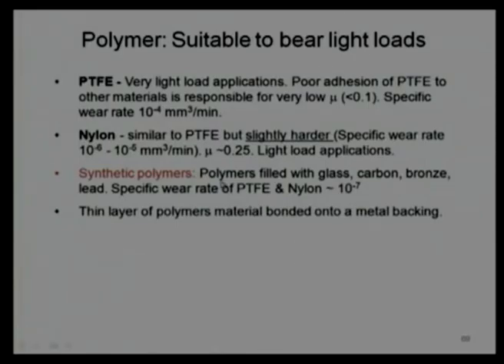That is why we are saying that if PTFE is mixed with glass or carbon fibers, they increase their strength. When they increase the strength, the wear rate goes down. And it has been observed the specific wear rate turns out to be only 10⁻⁷ compared to 10⁻⁴, almost 1000 times increase in life when we are using synthetic polymers. This is mentioned over here.